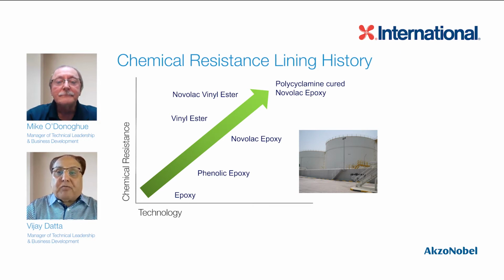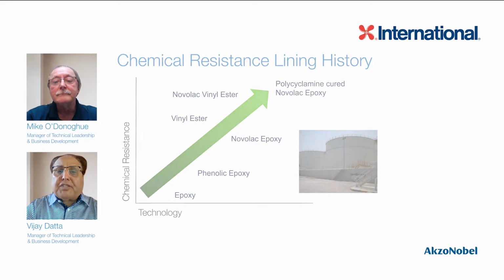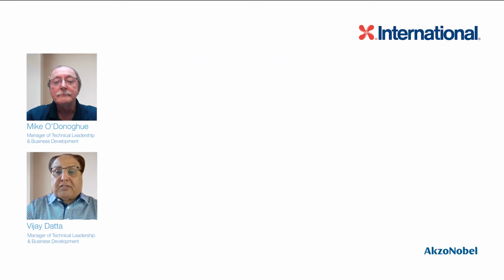As the need for aggressive chemicals arose, so did the development of the tank linings. So we moved into phenolic epoxies, Novolac epoxies, Novolac vinyl esters, and the latest development is polycyclamine cured Novolac epoxy. This is a huge innovation, both solvent-borne and solvent-free. And that's what Enviroline 376 is. And we're going to be talking about Novolac epoxy coating cured with polycyclamine.